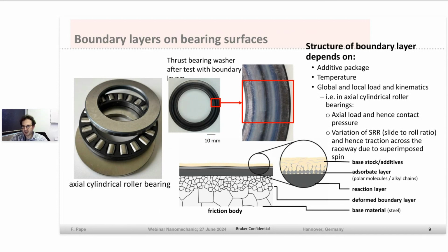And what we can see here in this image on the bottom, we have the adsorbate layers, which we can investigate also with our time-of-flight secondary ion mass spectrometry, and then the chemical reaction film, the reaction layer, which is very important to avoid wear.